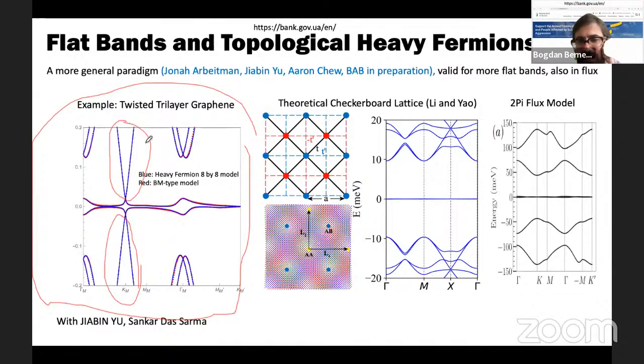If I didn't have this, it would be basically similar to the twisted bilayer, but I have this, which couples to the bands, and the displacement field pulls the Bistritzer-MacDonald flat bands away and tries to link them with the Dirac. What I want you to see is that the red and the blue lines are the heavy fermion model versus the actual Bistritzer-MacDonald type models that are used for these trilayers. And you can see the matching is excellent.